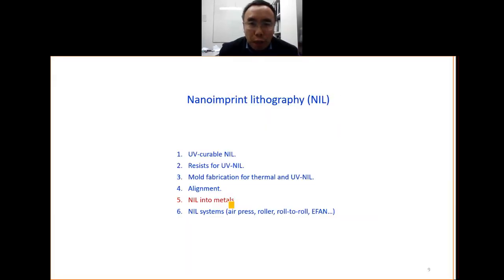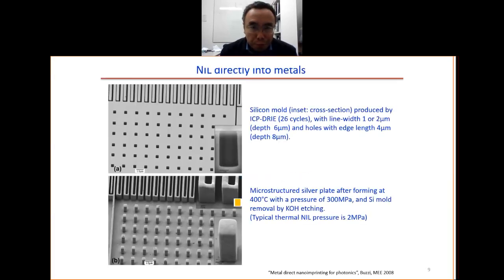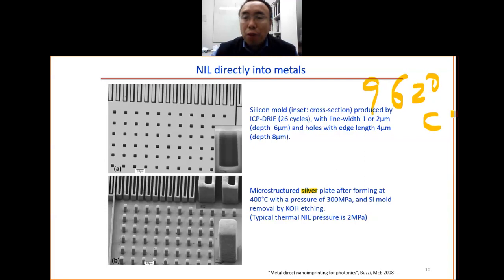So now we look at imprint into metals. In this first example, we do the imprint into silver. We know that silver has a melting temperature of about 962 degrees. But here the imprint is done at a lower temperature, 400 degrees. But the pressure is very high.